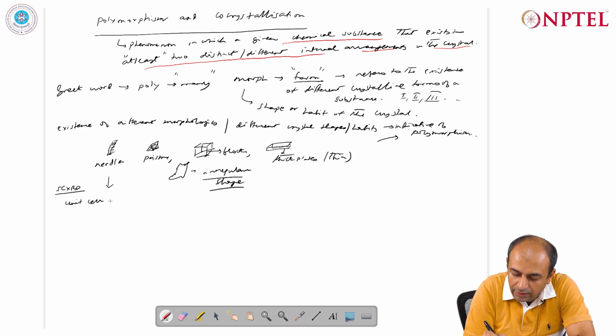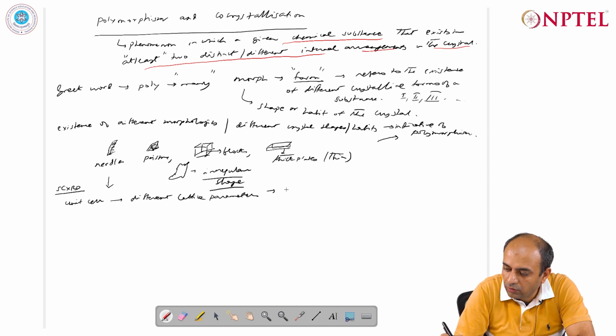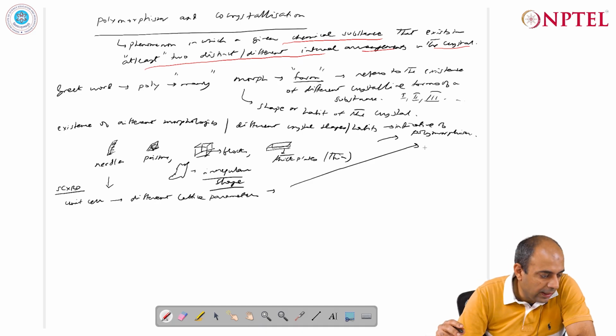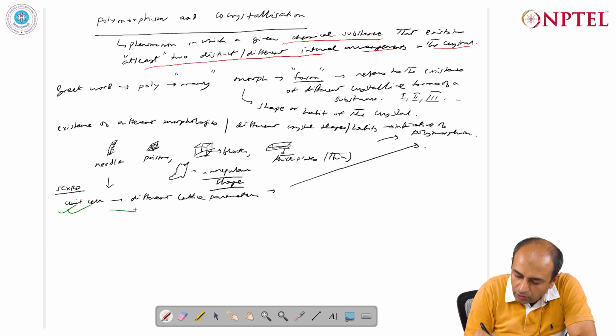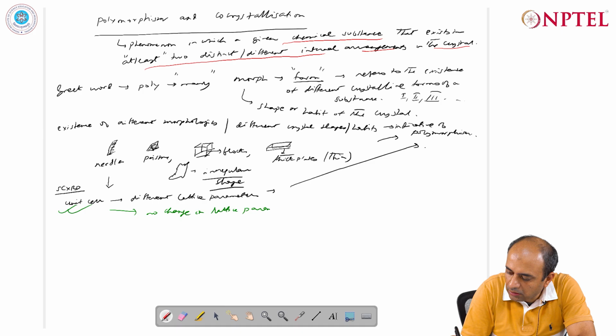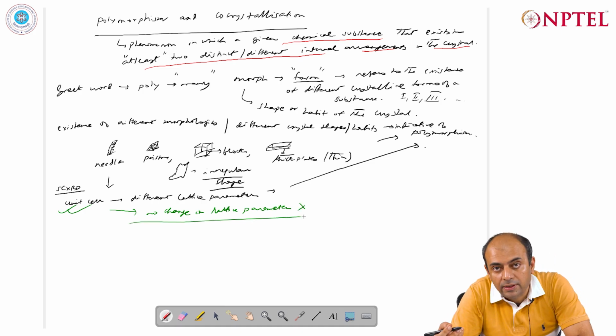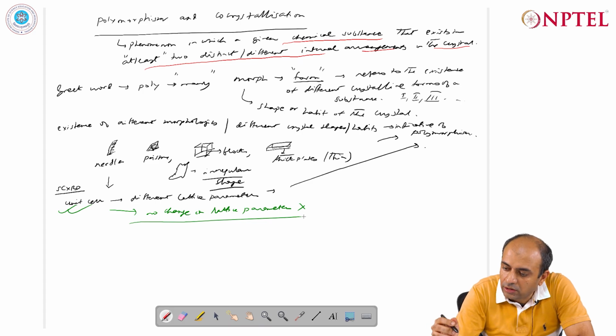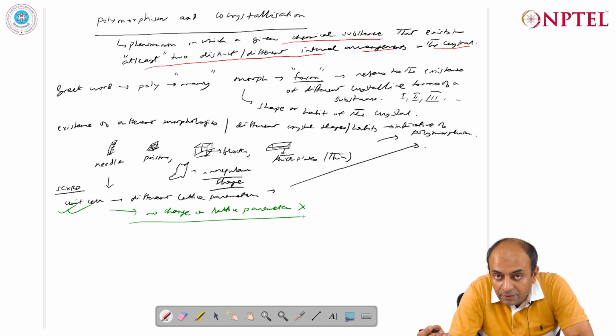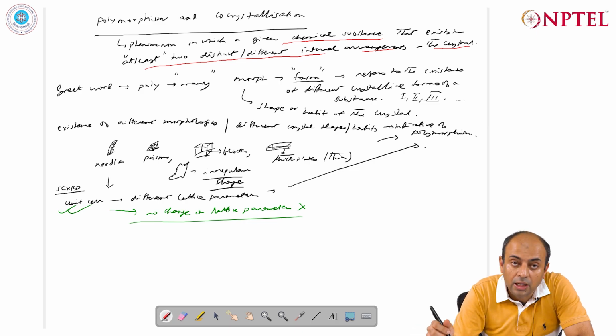And the next way to check for polymorphism is to look at the technique of single crystal X-ray diffraction, where you determine the unit cell, and determination of the unit cell tells you whether you have polymorphism or not. So if you get different lattice parameters, this is a very strong indication of polymorphism. It is also possible that you can have different morphologies, but when you do the unit cell check, no change in lattice parameters takes place. So because there is no change in lattice parameters, it is not indicative of polymorphism, because the internal structure, it refers to the fact that the internal structure is possibly, I am using the word possibly here, the chances are very, very high that possibly the internal arrangement of these crystals are similar.